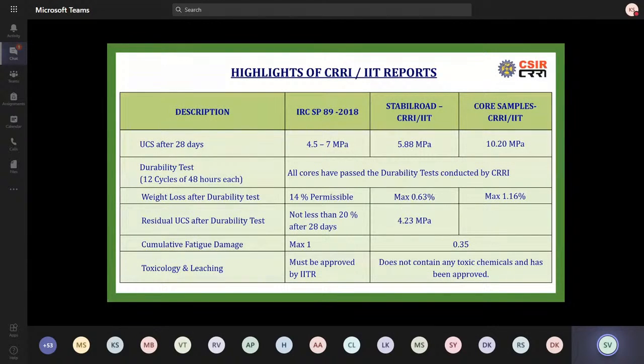Coming back to CRRI, according to SP 89-2018, the UCS after 28 days should be 4.5 to 7. In the lab at CRRI, they've got a strength of around 5.88 on average. But actual on site, we have achieved 10.2. We observed this in almost all the roads we have done so far, where the test results are much higher than what we achieve in the lab.